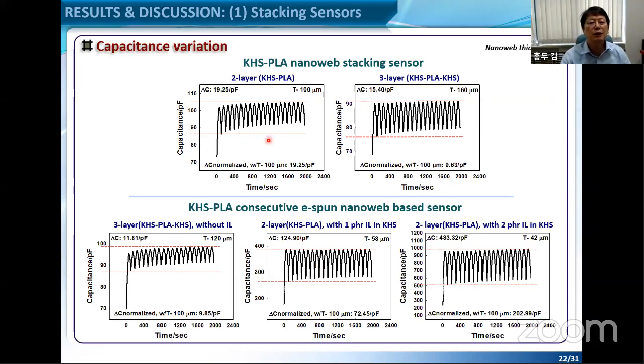As you see here, we simply attach the KHS and the PLA nanoweb to each other. All the fibers are very similar, but in this case, with a small amount of ionic liquid, the bottom case, the consecutive electrospun system, has very good performance in terms of capacitance change. This is because PLA is normally a somewhat brittle sample, which is why it has some creep behavior. But if we add a small amount of ionic liquid, KHS somehow accepts that kind of brittleness with elastic behavior. Okay.